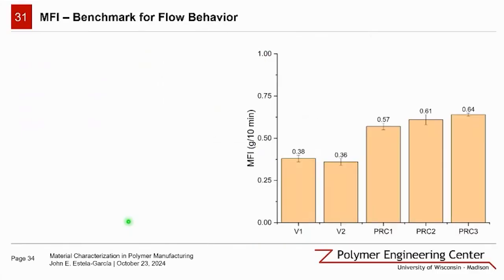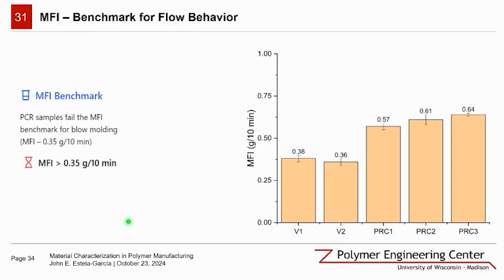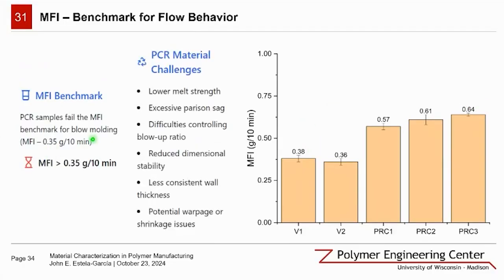Melt flow index here serves as a crucial benchmark for assessing flow behavior. What we're observing here is that our PCR samples fall short of meeting the industry standard MFI benchmark for blow molding. And this deviation from the benchmark has significant implications for melt strength. Lower MFI materials tend to exhibit higher melt strength, which is essential for maintaining that parison shape as discussed earlier.